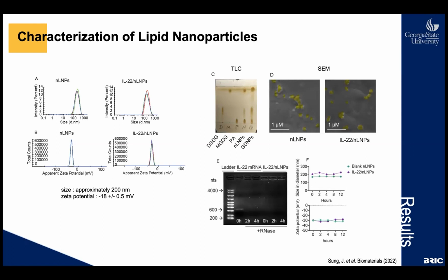To test this, we incubated naked IL-22 mRNA and encapsulated IL-22 mRNA in RNases for up to 4 hours, and then ran the electrophoresis to observe whether IL-22 mRNA survived or not. This very first lane is mRNA without the RNase exposure, and the neighboring samples are exposed. As we can see in this image, none of the IL-22 mRNA is detected when it is not protected. But we see white residues from the lipid nanoparticles at the top of the gel, and no destroyed mRNAs are seen at the bottom. And these two graphs on the right side show that the size and zeta potential were stable after long hours of incubation at room temperature.